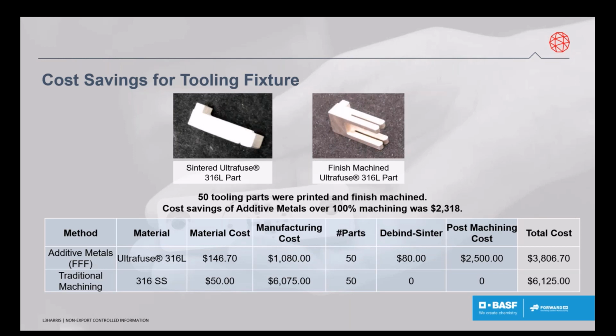So you can see in the chart here on the savings, material-wise, it cost more for the UltraFuse material, but the manufacturing cost was a lot less. The number of parts we printed were 50. Of course, we had a debind and sintering cost and a post-machining cost, and the machining cost was to machine the bottom and then polish it and actually EDM the slot in the 50 parts. So we saved about $2,318 making 50 of these.